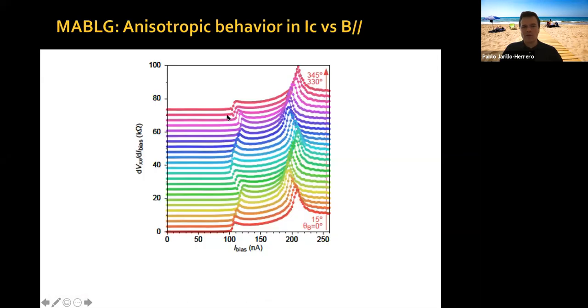If you want to look at the actual critical current curves, here you have the differential resistance as a function of current bias. You see this is zero, this is the superconducting state, and then you have a switch. Interestingly, for some devices and in some doping ranges, you have two switches. Let me not comment too much on that at the moment. What I'm varying between the different colors here is the angle of the magnetic field. And as you can see, you have an oscillation. In fact, this behavior can be well described by a cosine, and this oscillation gives you 2 maxima, which means you have an ellipse also in the critical current versus parallel magnetic field.